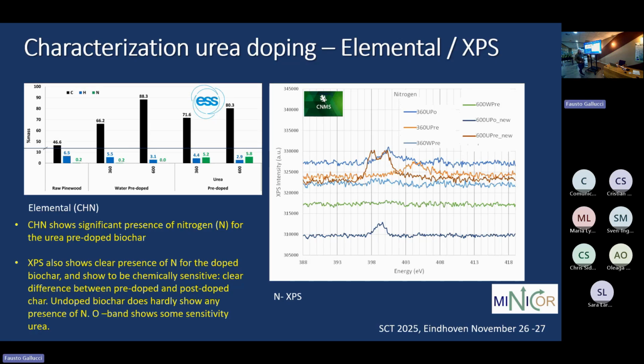XPS also gives very interesting results. For the water-doped and dried sample, you don't see any nitrogen at all. When you go up with the post-doping at 360, it's this one here. And then you have the 360 pre-doping, which is this orange. You see that they are different. The interpretation of this is preliminary, so what I say may not be strictly correct, but this is probably connected to oxygen groups. When you go up in temperature, you will also see differences.